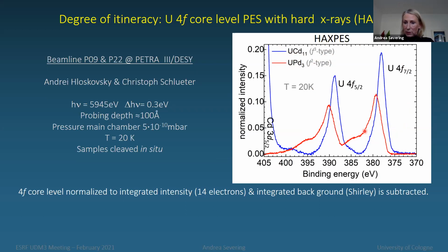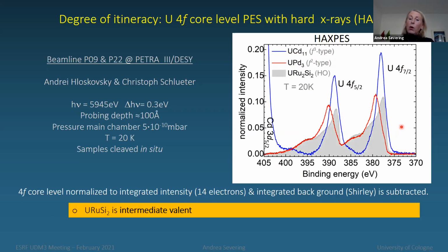They look distinctively different in HAXPES. And if I'm now overlaying the uranium ruthenium two silicon two core level data here in gray, our interpretation is the uranium ruthenium two silicon two has features of both, of the cadmium 11, but also of the uranium palladium 3. Hence, it is intermediate valent. It is somewhere in between F3 and F2.